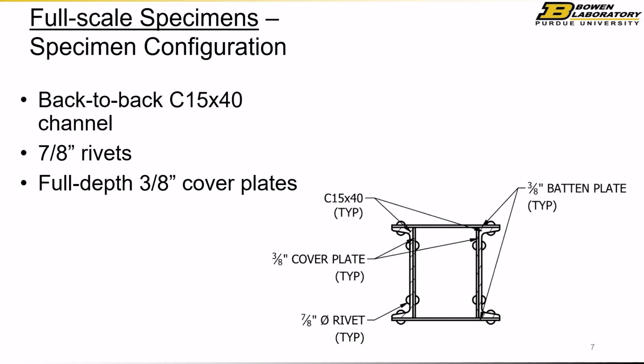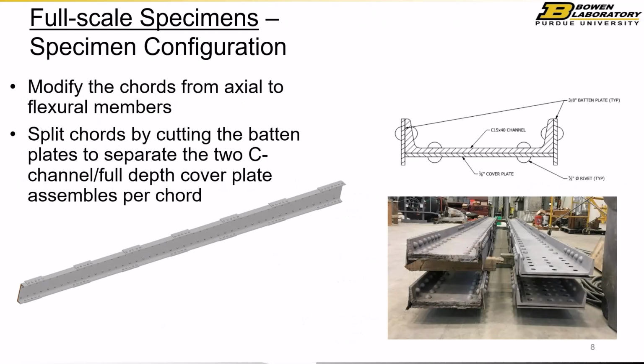But they're the typical built-up member you would see. These were rolled channels with cover plates, right? So that's where our pack-out corrosion ended up happening, was where we had the cover plates. So we converted these then to flexural members. Right? So we take the truss, the chord, we separated it into two halves. And then we treat those halves as flanges with a constant moment region, so the flange is effectively in uniform tension over a given length.